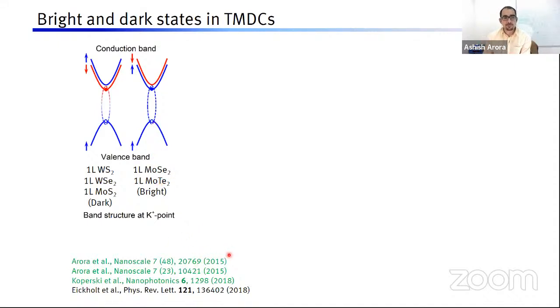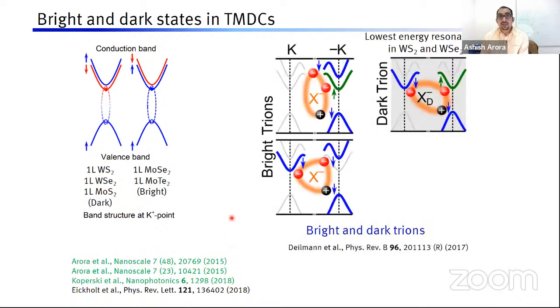This was found in 2015 by us. Now, if we create trions, the band structure is a little bit complicated, because now you have three particles and two types of valleys: one is the K valley and one is the K prime valley. Let's suppose we have tungsten disulfide and we create a bright exciton by putting a hole in this band and an electron in the top band, which is a bright band. Then we can put an extra electron either in this band or in this band. So we can have two types of bright trions.